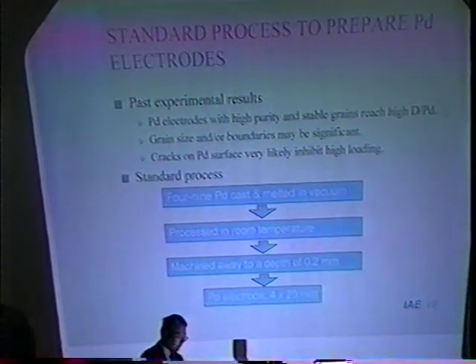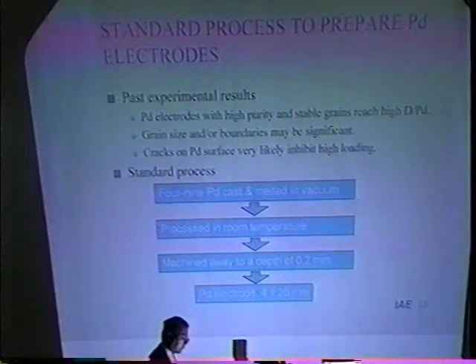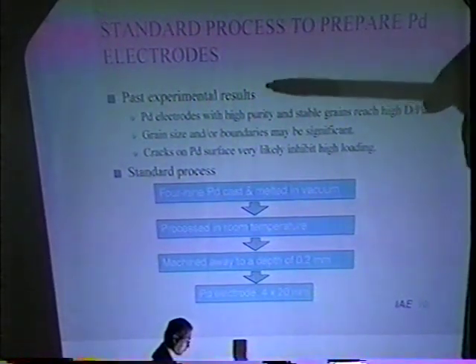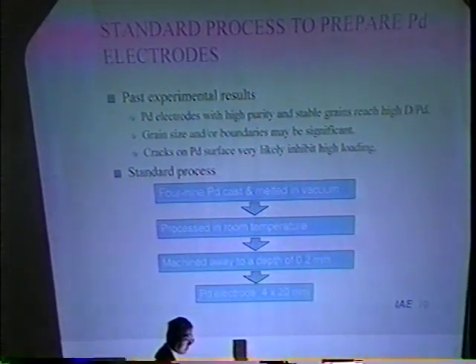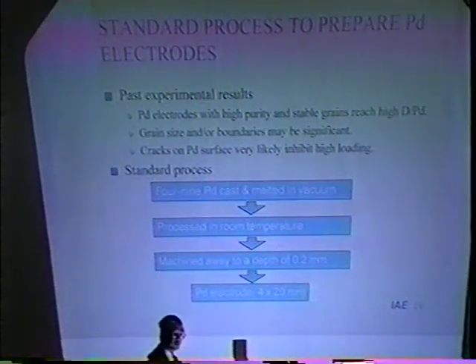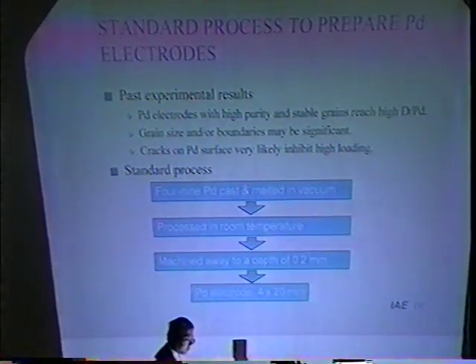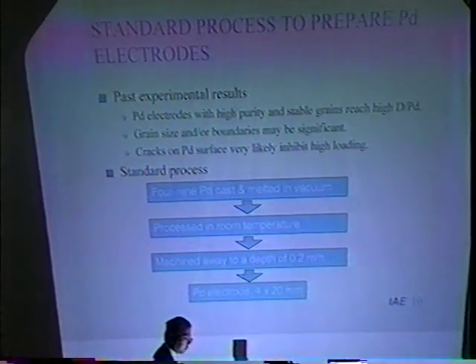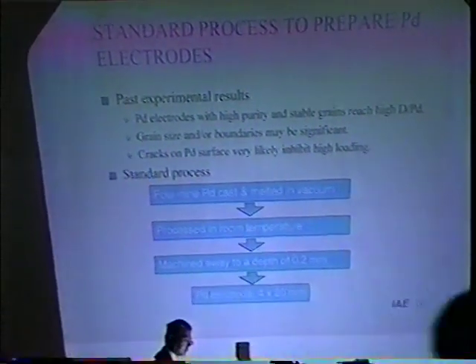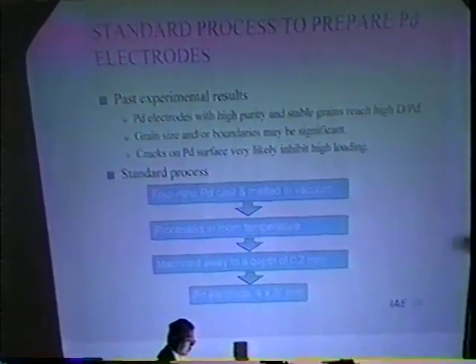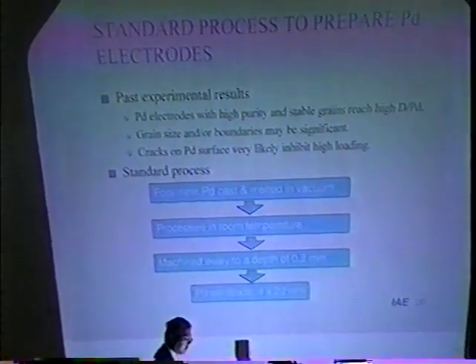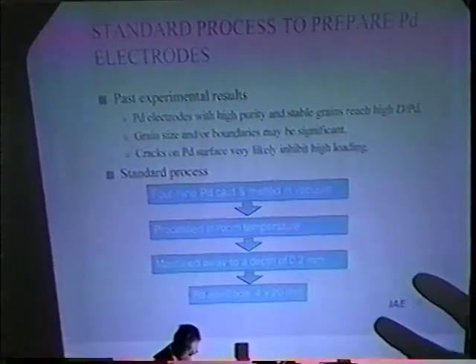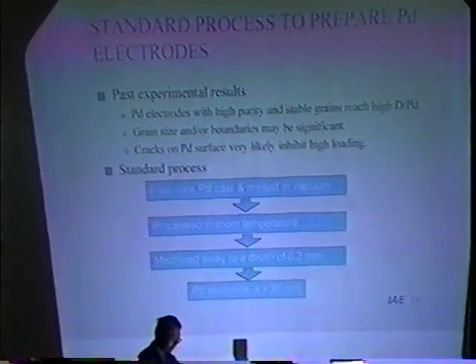A standard process to prepare palladium electrodes was determined based on the first experimental results. Palladium rod with high purity and stable grains is important, and grain size and grain boundaries may be significant. And cracks on the palladium surface very likely inhibit high loading. Therefore, palladium rods were made of 4-9 palladium cast and melted in vacuum and processed at room temperature, and their surfaces were machined away to a depth of 0.2 millimeter. Details of this process will be presented by Dr. Asami in this session.